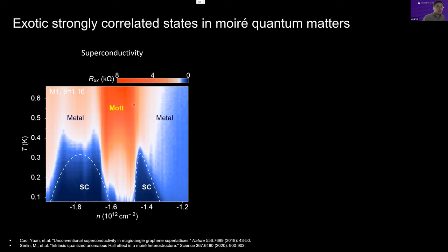But actually an insulating state surprisingly appears, which is due to the strong electron interaction at this moiré superlattice scale, okay? And if you slightly dope the Mott insulator, another quantum phenomenon actually arises. It becomes a superconductor. So that actually corresponds to what is called the doping-the-Mott-insulator picture of high-Tc superconductors. Considering this low carrier density in a metal, and the comparably very high, actually 300 millikelvin, superconductivity transition temperature, this is actually a very high temperature for a superconducting transition.